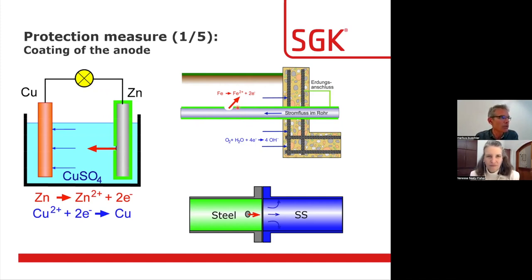If you coat it and only have one tiny hole in the coating, the entire current gets concentrated here, and you have holes within years. So this leads to the paradox conclusion: these pipelines perforate because we have improved the quality of corrosion protection based on a coating which hasn't been defect-free.